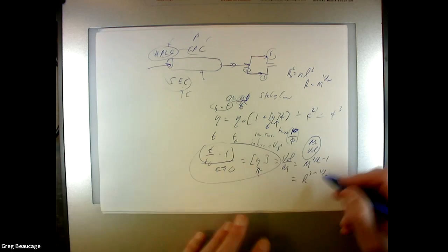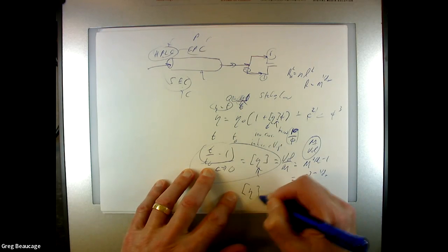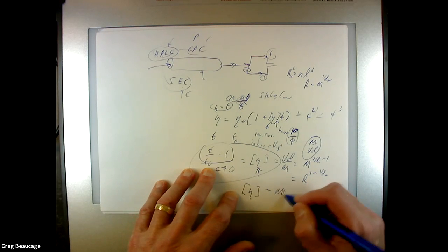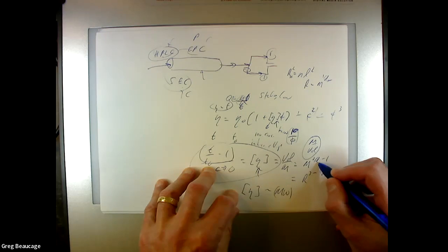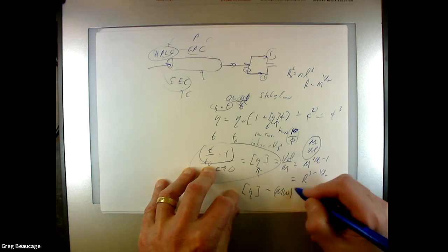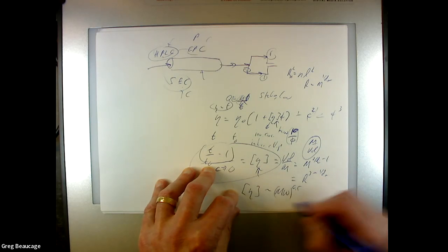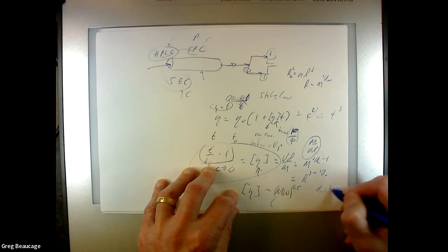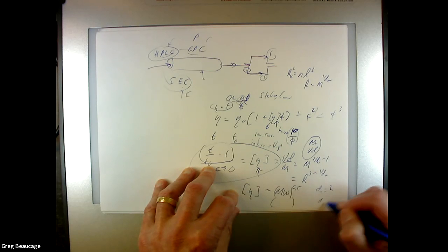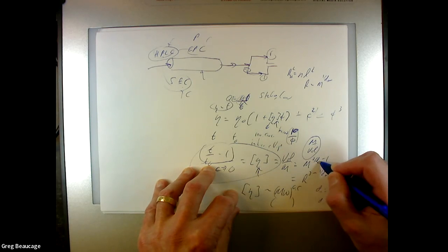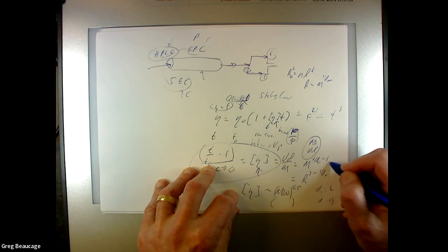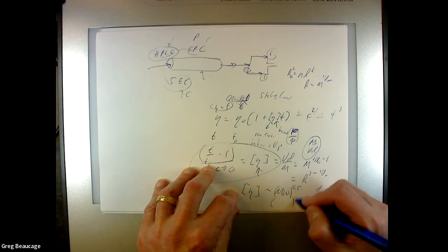So this number, this intrinsic viscosity, is going to be proportional to molecular weight. Yes, since you're trying to get molecular weight usually. And if dF is 2, it's 3/2 minus 1, which is 0.5. If dF is 5/3, you have 9/5 minus 5/5, which is 4/5, or 0.8.